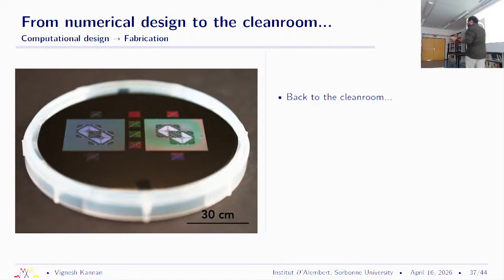The one thing that can happen, which you saw before, is when we do the etching, there is temperature buildup, which means the base layer, which is the solid layer, could warp under temperature. So it could have a heterogeneous temperature distribution, and then you could have some warping, which basically warps the film on top. With these specimens, we did not have that problem. With our large specimens, we did have a little bit of curvature in our top film, but then we were able to verify because we have a microscope that essentially observes the film and observes the base layer. So we can verify that there is a gap between the two. Now the topology of the slow curvature of a large film, that's something that we can control by simply controlling the time that we do etching through, because then you have to control the temperature.